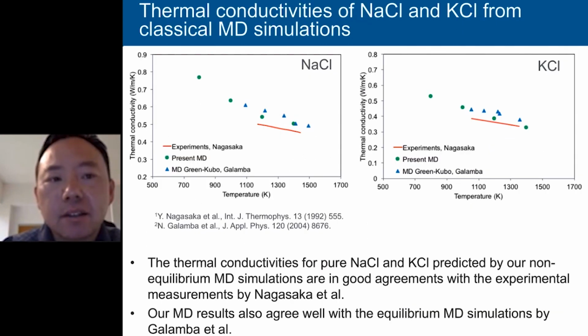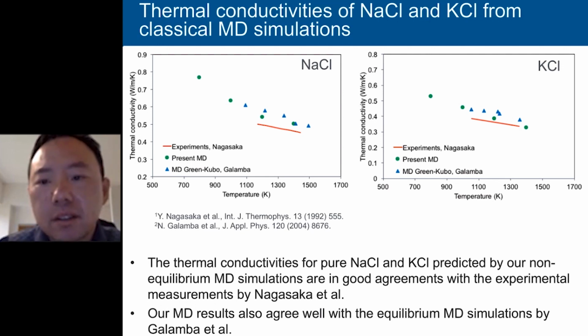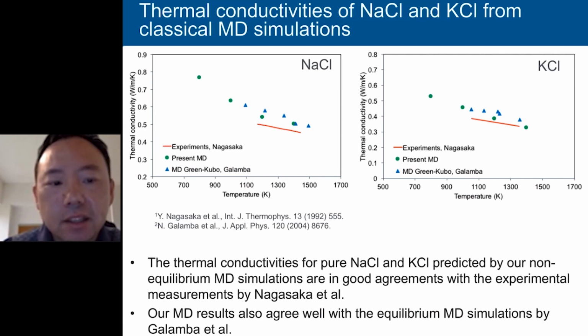And finally, let's go to the thermal conductivities. Here, experimental data only exist for pure sodium chloride and potassium chloride, which are shown in the left and right figures. You see that the MD simulation gives excellent agreement with experimental data. I also added another literature calculation of thermal conductivity using the Green-Kubo method, shown as the blue triangles. Here you can see that both methods agree with experiments.